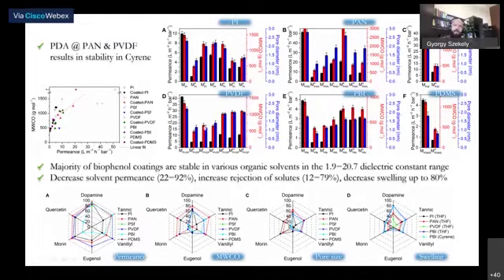So what you can see here is we have values all over the place, basically. We have lower values, we have higher values, and it changes with the different types of coating materials, natural materials that we use. And here you can also see the different coating materials, and you can see that the data changes quite drastically over the different membranes.